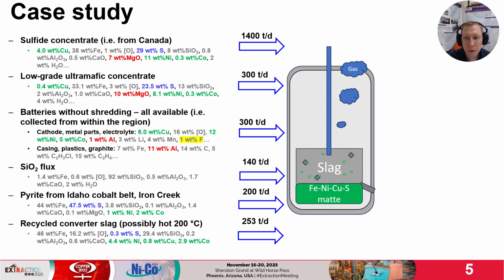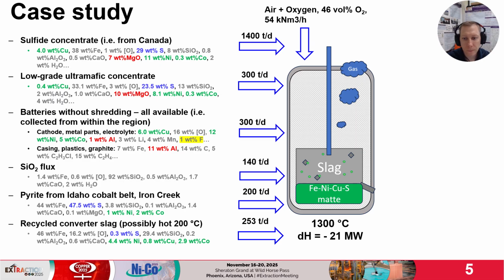And the converter slag from the next step must be recycled back. The blast is moderately enriched air with 46 volume% oxygen. Operating at 1300 degrees Celsius results in 21 megawatt heat loss. In other words, the heat is produced and must be released into the environment. The process does not need fuel for normal operations. Energy balance can be controlled by oxygen enrichment.